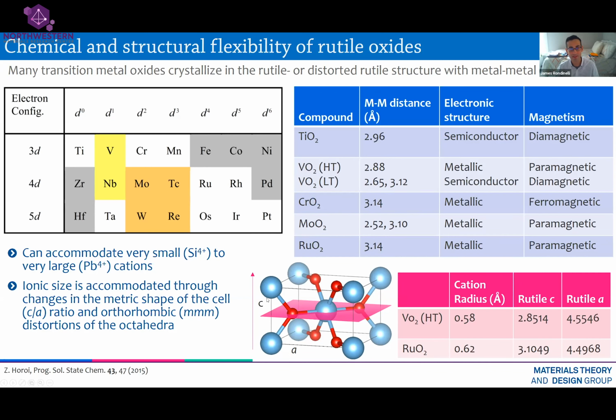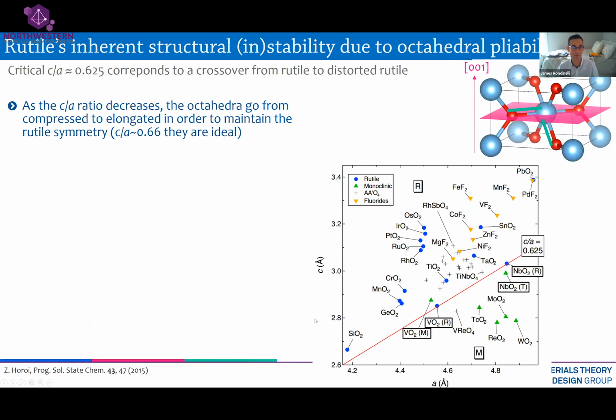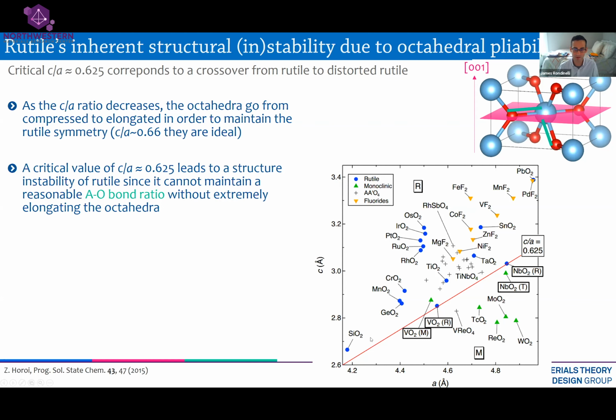And it's known, and here's sort of where the abstraction comes from, that this ratio, this length C over this length A, will dictate whether or not any of the materials in this rutile family can exhibit a structural transition and or a metal insulator transition. So there's a huge number of compounds on here. And I'm just going to move a little bit more quickly through this part. But what you can see is that as a function of C versus A, if you're in a range where the ratio C over A is large like this, all of the structures adopt the rutile structure, meaning the distance between metal atoms is equidistant everywhere.